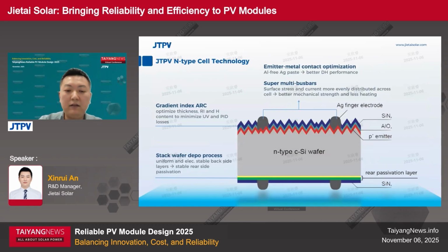Cell technologies not only impact efficiency and power output, but also affect reliability. For example, our stack wafer deposition technique forms a uniform and electrically stable backside surface, free of blisters, and it also facilitates reliable rear side passivation. And the front side gradient index anti-reflection coating optimizes the thickness, refractive index, and hydrogen content within each layer to reduce UV and PID losses.